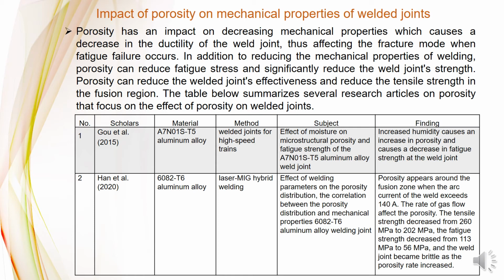The table below summarizes several research articles on porosity that focus on the effect of porosity on weld joints. Number 1, Gou et al. Material: A7N01S-T5. Method: welded joint for high-speed train. Subject: effect of moisture on microstructure, porosity and fatigue strength of the A7N01S-T5 aluminum alloy welded joint. Finding: increased humidity causes an increase in porosity and a decrease in fatigue strength of the welded joint.